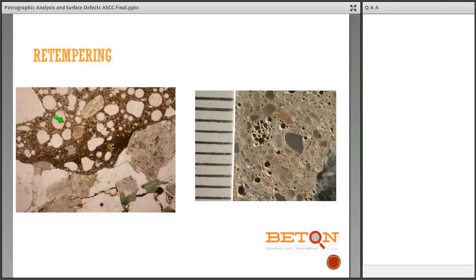Similarly, we can tell when water has been added at the site. You can see here in this notch, there's a darkened area of higher water to cement or low water cement ratio paste, and surrounding it is an area of high water cement ratio paste.